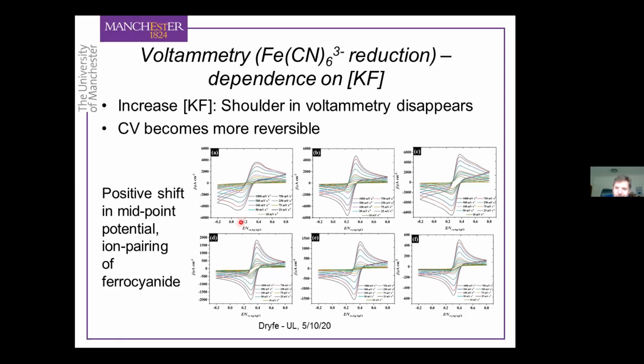And so here we're showing the ferrocyanide couple, just a simple macroscopic CV on basal plane graphite. Again, same concentration of the redox active molecule, but increasing the concentration of KF. So we'll go from 0.5 molar to the same concentrations as I showed you just before, 1 molar, 5 molar, 10 molar, 13 molar, and 17 molar. And you can see two things. Firstly, if you look at the current density we're measuring here, it's decreased by an order of magnitude. It's gone from 6,000 microamps per square centimeter to 600 microamps per square centimeter.